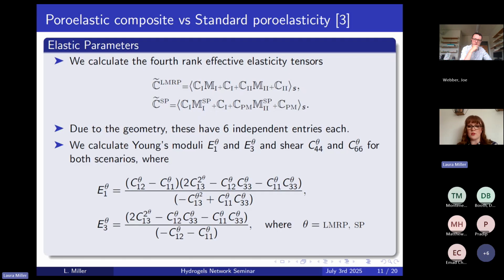And I want to calculate my Young's moduli and shears for both of these scenarios. So again, the fact that we have the 6 independent entries and the geometries that we have are the reason why I'm only mentioning Young's moduli E1 and E3 and shears C44 and C66. So these had to be obtained by doing an inversion of an elastic compliance tensor and manipulating various tensors, but we got our new expressions for our Young's moduli. And I'm using this theta subscript just to say that these are the components coming from the elasticity tensor for one model and the other model. So we've got two cases.